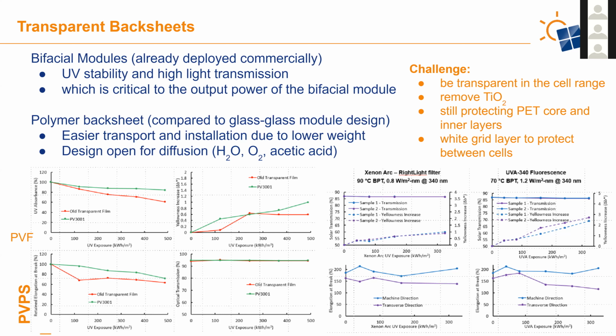One challenge of these transparent backsheets is that you have to remove the TiO2 that's typically added to backsheets to protect the PET core. So you still need to be able to protect that PET core, if there is one, or any inner layers. Oftentimes they're adding a white grid layer to protect between the cells so that area isn't completely transparent.